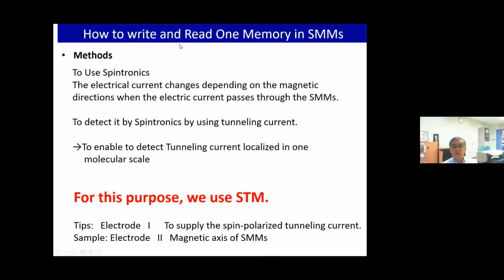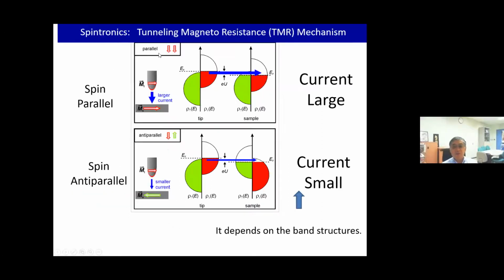So how do we write and read one memory in a single molecule magnet? For this purpose, we use an STM. The tip is electrode 1, the sample is electrode 2. So as I told you, this is TMR. When the spin of the tip and the spin of the single molecule magnet are parallel, it is high conductance; anti-parallel, low conductance. Switching between high and low conductance in the TMR.